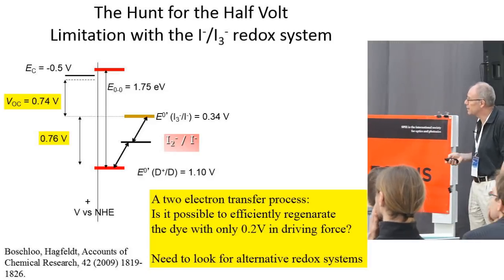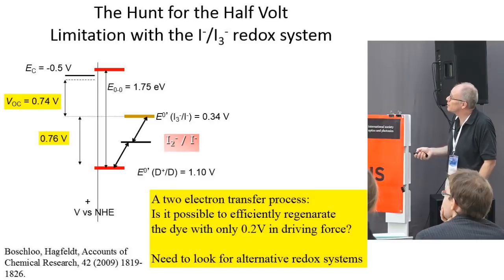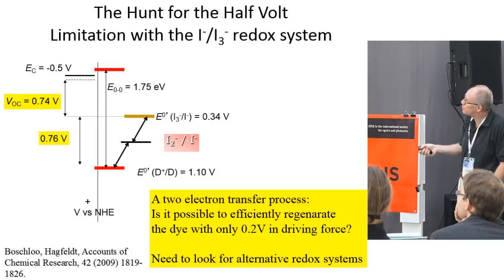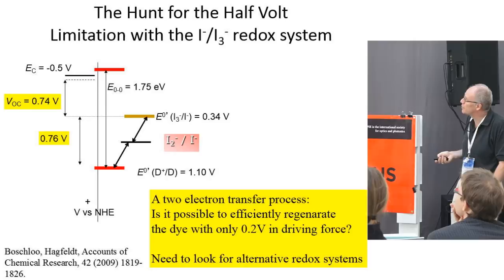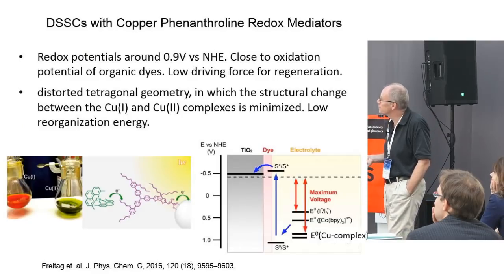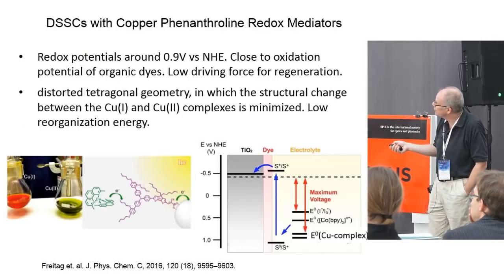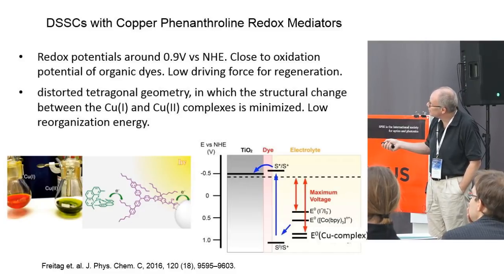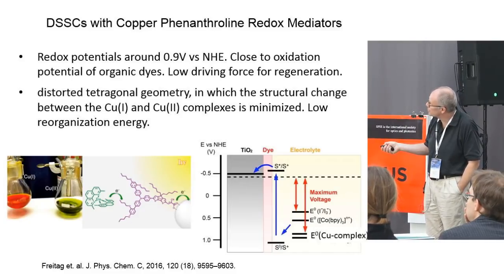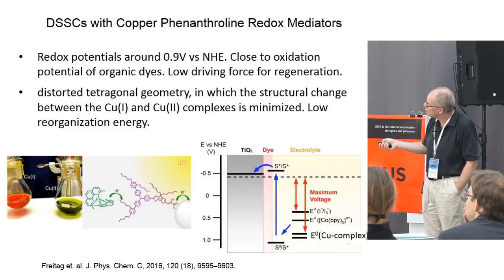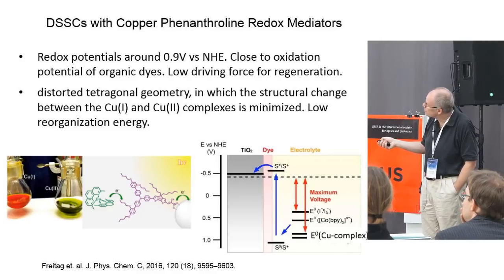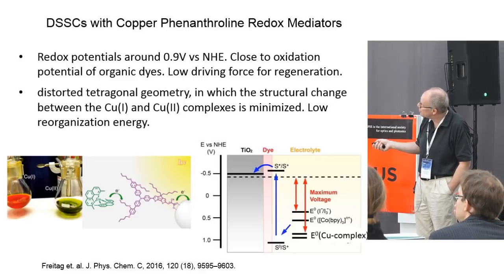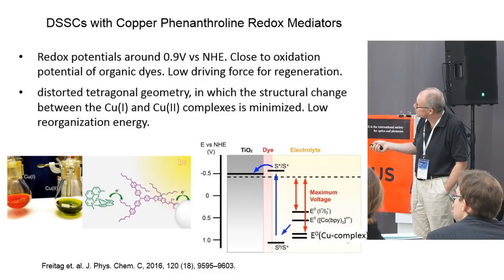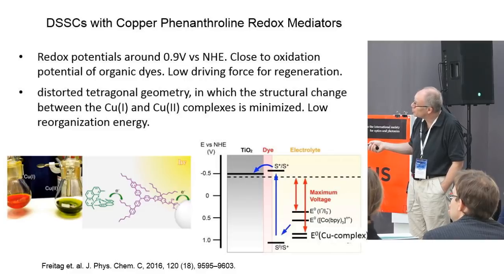And I will make that very, very short. We managed in Uppsala to find a way that the dye itself can passivate that recombination. And we started to work on new redox couples. And here is the diagram again. Here's the redox potential of iodide and the gap to the oxidized dye here. And then with the new dyes we developed, we could use cobalt complexes, and then you can increase the voltage by going this way. And nowadays we are focusing a lot on copper complexes instead, where we are really closing this gap from 0.7 to about 0.2.